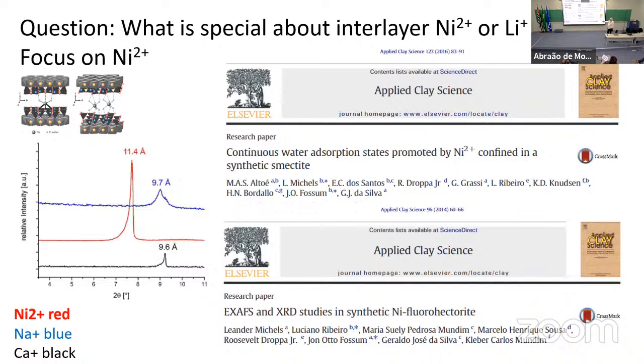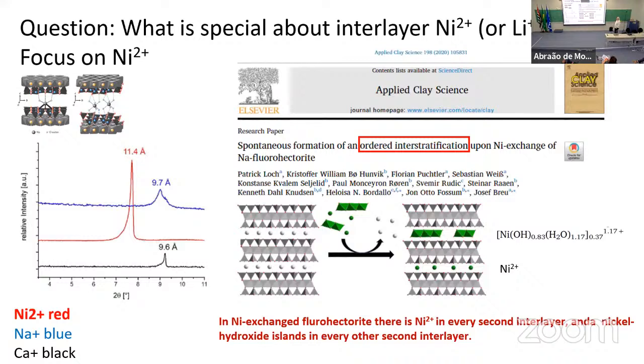But in any case, we had observed previously that when we dry the nickel samples, get rid of all the water, it does not collapse to one nanometer distance between the platelets. It stops at 11.4. This we did not understand. In this paper, we understood it. Actually, it is due to this ordered interstratification that I mentioned. In the original sample, we have sodium ions in these interlayers. When we exchange for nickel ions, it turns out that in every second interlayer, we get nickel hydroxide, and in every second interlayer, we get nickel. The average of those two d-spacings gives 11.4, and that doubles the unit cell distance. It's not shown here, but in the nickel case, we have a superstructure peak corresponding to a larger unit cell.